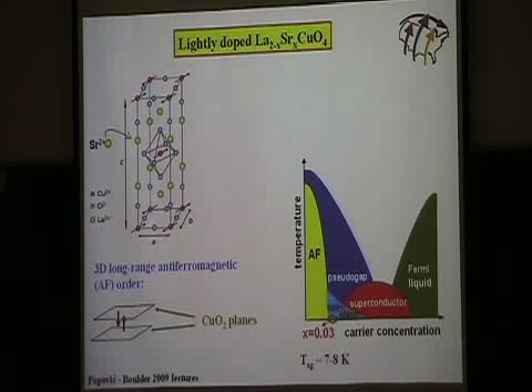Now, because of the details of the lattice structure, the total moment is slightly out of this plane. So there is a small component which is perpendicular to these copper oxygen planes, small ferromagnetic components. And these ferromagnetic components in neighboring planes are opposite, so they're also antiferromagnetically ordered, so the total magnetic moment is 0 in the material. Okay, so this is the undoped material.